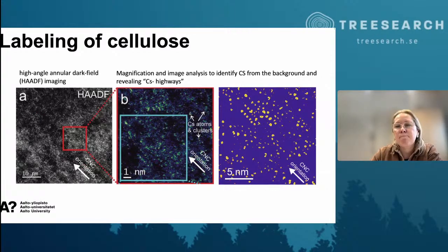And with the analysis, which is also what Daniel did, we could see that the diameters of these spots are some 100 to 150 picometers. So we have this kind of a distinct pattern that emerges, and then with image analysis, or AI-guided image analysis, we can identify even more.